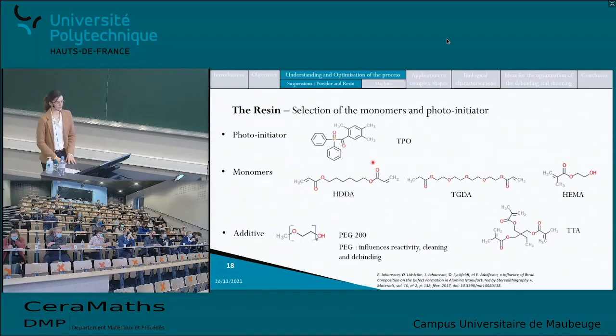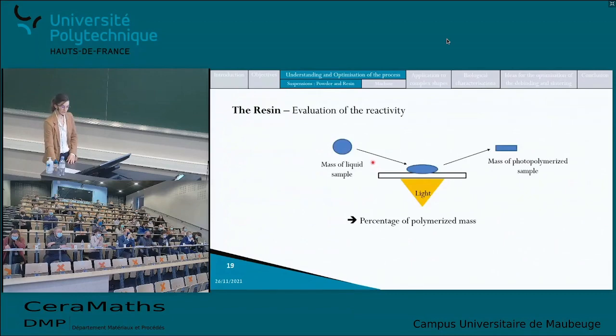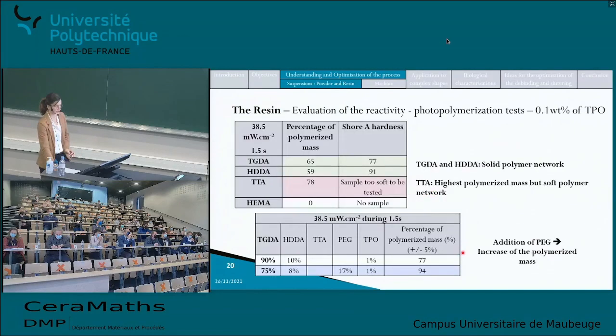So I did a better evaluation of the reactivity. So basically, I measured the mass of a liquid sample and I placed it on a plastic film, illuminated it from below with the DLP of the machine, and measured the mass of the photopolymerized sample, calculating the percentage of photopolymerized mass. The results were these ones. So the TGDA and the HDDA provided photopolymerized mass around 60–65%. The TTA seemed to provide the higher photopolymerized mass with 78%.